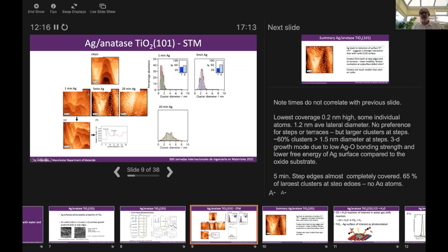After 5 minutes, we've got this situation. We've now got more preference for steps compared to the terraces. The cluster size has increased to about 2.4 nanometers, but still only 0.7 nanometers high. And then finally, after 20 minutes, it's hard to define. There are a range of cluster sizes on this image here. But now the average cluster size is about 4 nanometers. So the cluster sizes that form are about half what we saw on the rutile titanium dioxide.